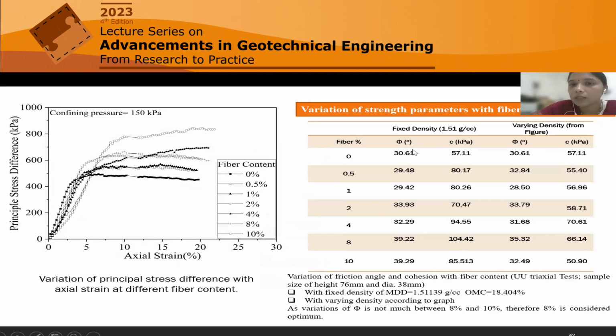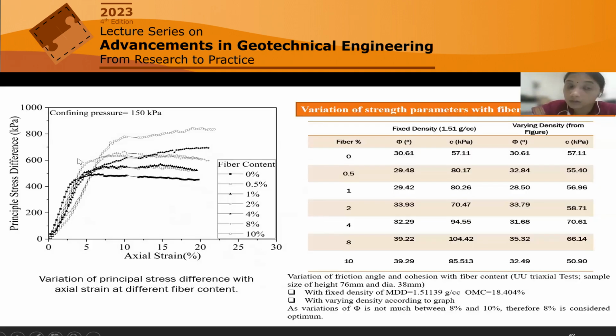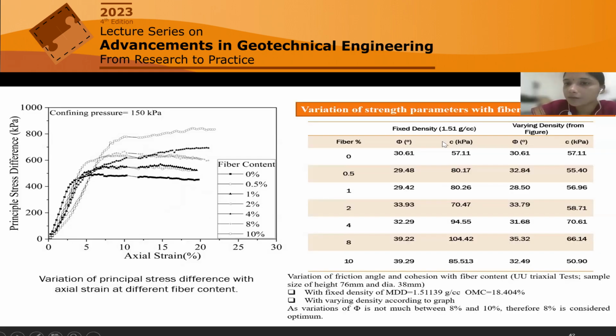And in the table on the right side you can see the strength parameters, friction angle and C value. Two cases we have considered for the triaxial test. In one, the density is fixed at 1.51, the density of the source MSW fines. In the other, the density varies, because for different fiber content we will have a different compaction curve. For example, for 10% the MDD is nearly 1.35 or so. So we performed the triaxial test considering both: varying density from the different fiber contents, and constant fixed density, that of MSW fines at 0%.